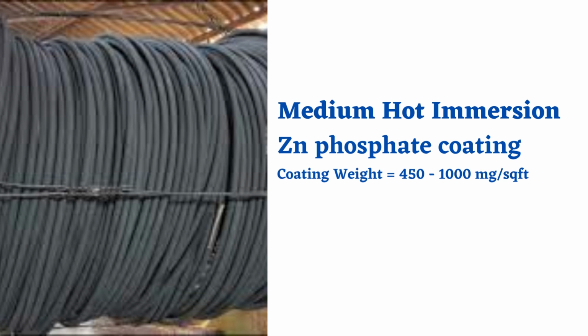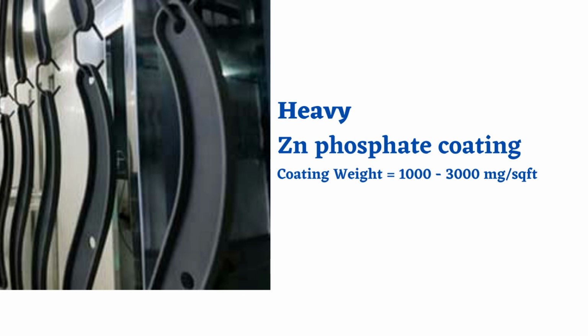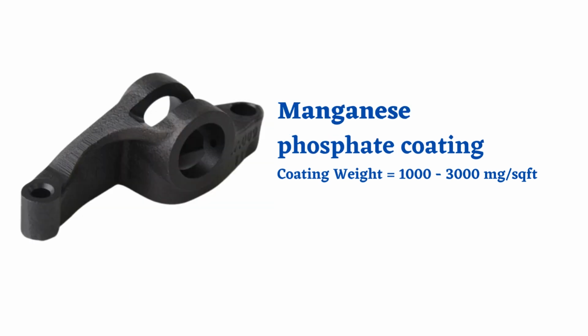Medium hot immersion zinc phosphate coating forms 450 milligram per square feet to 1000 milligram per square feet, and heavy zinc phosphate coating forms 1000 milligram per square feet to 3000 milligram per square feet. Manganese phosphate coating ranges from 1000 milligram per square feet to 3000 milligram per square feet.